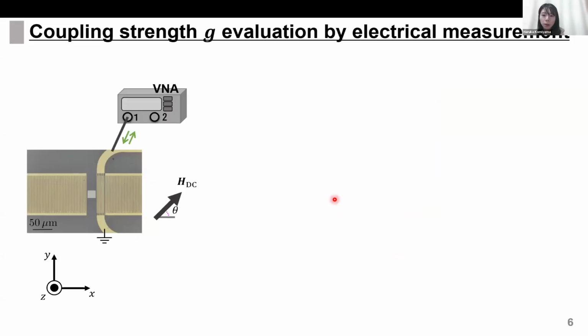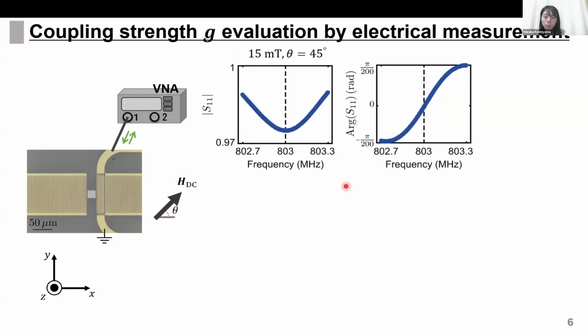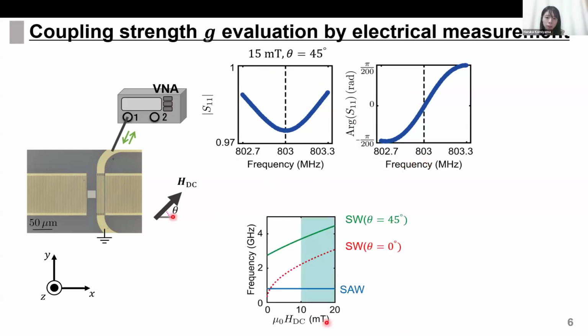First, we performed electrical measurement on the device and evaluated the conventional parameter, coupling strength G. Here is the measurement setup. A static magnetic field HDC is applied in the plane at angle theta, and the reflection coefficient S11 was measured using a VNA. This figure shows the frequency spectrum of the amplitude and phase of S11 measured when a magnetic field of 15 millitesla is applied at an angle of 45 degrees. You can see the amplitude dip and phase rotation around the resonance frequency of the surface acoustic wave. And here indicates the surface acoustic wave and spin wave resonance frequencies.